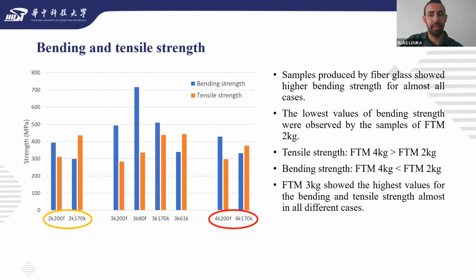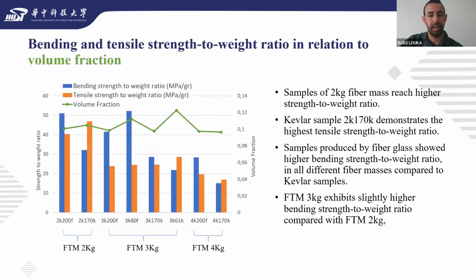Details for the bending and tensile strength to weight ratio in relation to fiber volume fraction are shown in this slide. Analysis of the tensile test results shows that samples of 2 kilo fiber mass reach a higher strength to weight ratio compared to the others for both materials. Kevlar sample 2K 170K demonstrates the highest tensile strength to weight ratio. The samples produced by fiberglass showed a higher bending strength to weight ratio in all different fibers compared to Kevlar samples. Now, fiber mass 3 kilo exhibits a slightly higher bending strength to weight ratio compared with fiber total mass of 2 kilo, while the fiber total mass of 4 kilo shows the lowest strength.